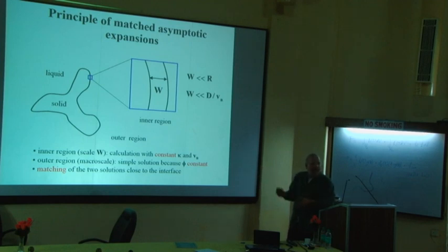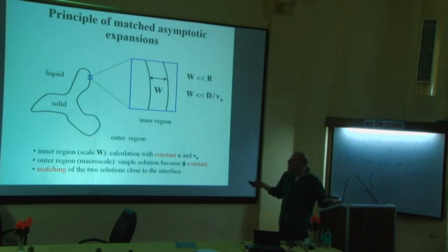So you can treat the variations of the diffusion field U as a small perturbation on the equilibrium state of the phase field. And if you look at the scale of the interface, there are also many other things that are constant. For example, as you see along this structure here, the radius of curvature varies. But if you look locally on the scale of the interface, it's as if you have a constant curvature. Also, the interface speed will certainly vary along the structure, but if you look at a local piece of interface, this speed will be approximately a constant.